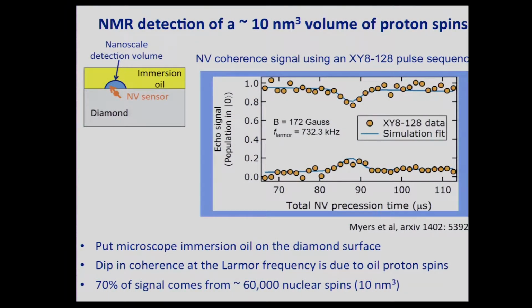And that characteristic frequency can be resolved in a type of measurement. Here, this is for the experts in magnetic resonance, this is an XY8 pulse sequence with 128 pulses that we've applied to the NV center. But basically, we're probing the coherence of the NV center as a function of wait time. When the Larmor precession frequency of the proton spins is matched to our wait time, we see a feature in our NV coherence signal. So this is a coherent signal that is due to this 10 nanometer cubed volume of nuclear spins in the oil in this case. So yes, this is immersion oil, but for us, we're getting closer to these wet and squishy systems.